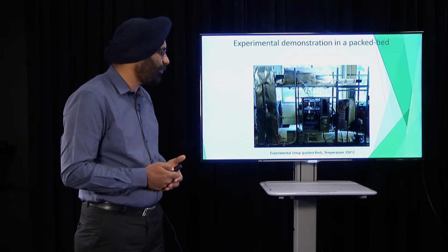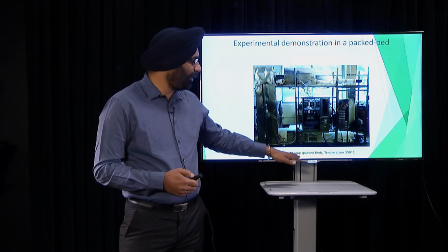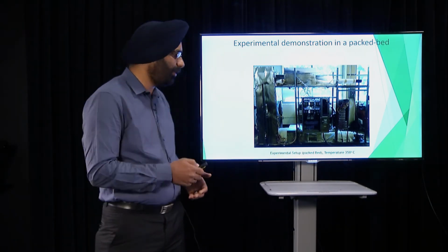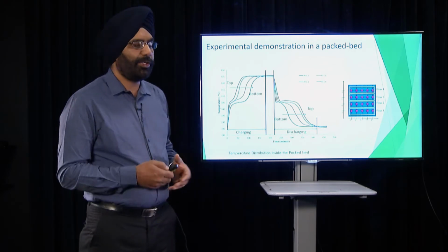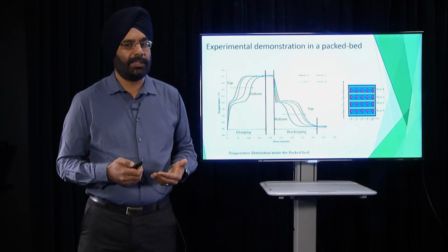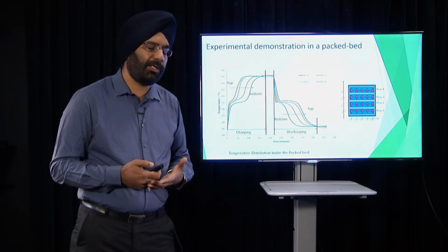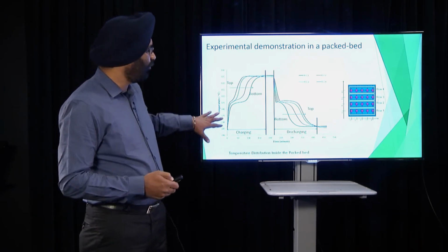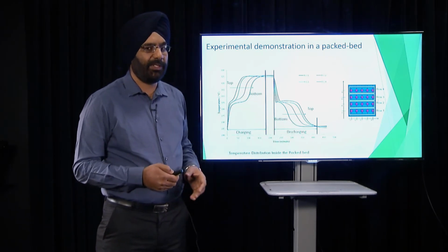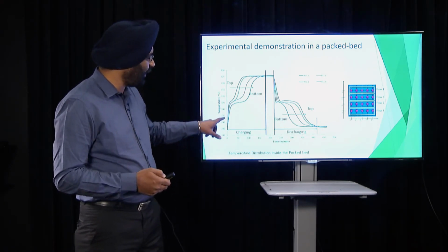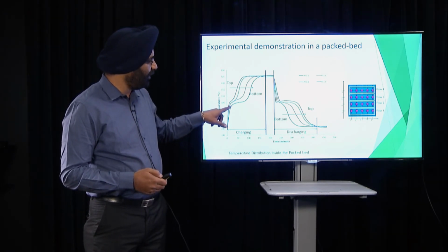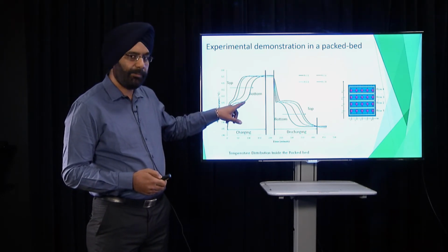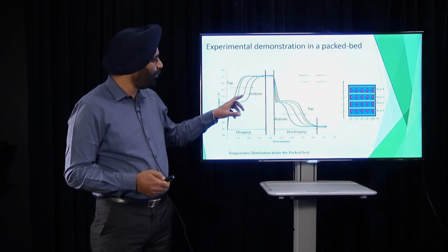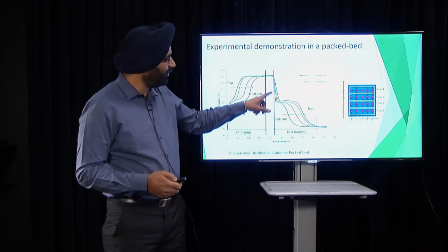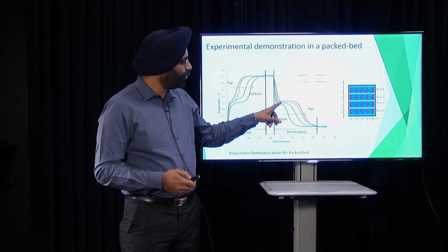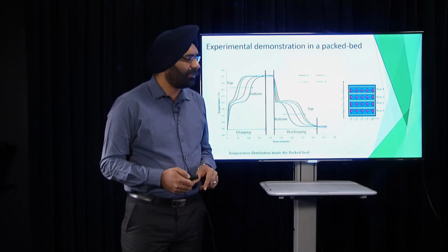So there are a large number of capsules inside, and this experimental setup was run at 350 degrees C. And the same thing which we did, we wanted to see how long the system took to completely charge and how long it took to completely discharge. So we monitored the system at different temperatures, and you will see again it shows the same phenomena. The temperature increases, and then when it's undergoing melting, it flattens out, and then again it increases. And this is the discharging, again the same thing, close to solidification it flattens out and then it decreases.